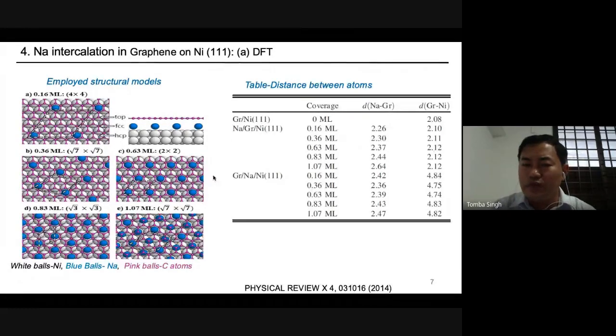Now coming to the important case, the intercalated graphene. Here, with the increase of the coverage, there is no change in the sodium-graphene layer distance and the graphene-nickel distance. Then overall, what is the important point from here? The distance between the graphene and the nickel in the pristine system is 2. But after intercalation, the distance between the graphene and the nickel is increased more than double, here it is 4.9.